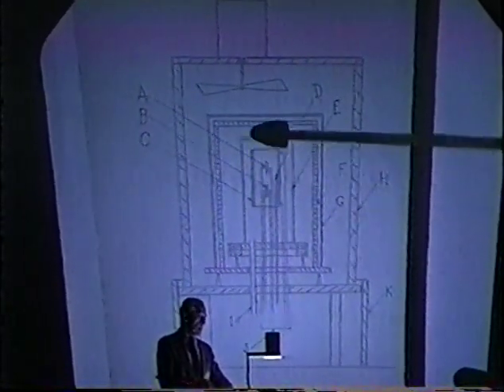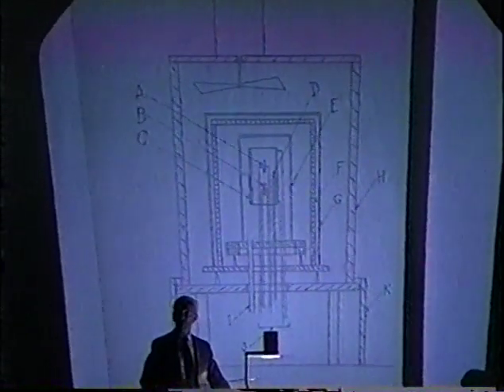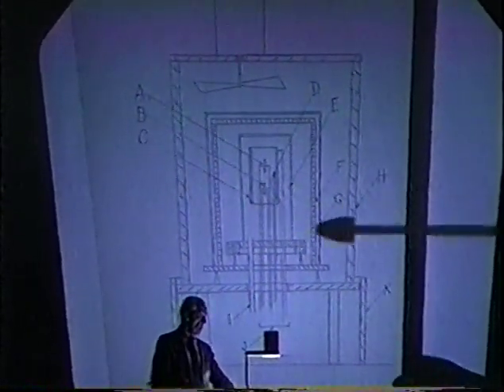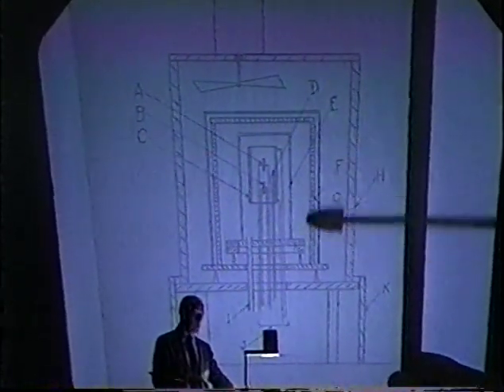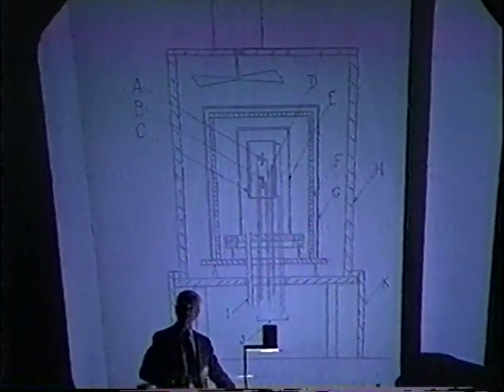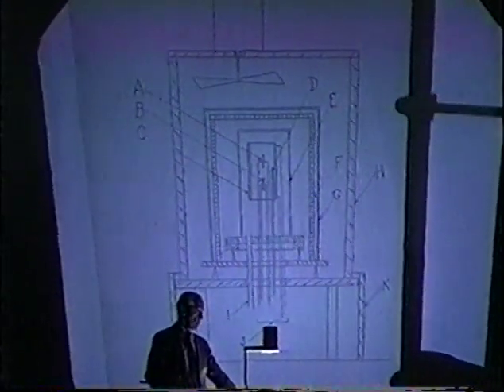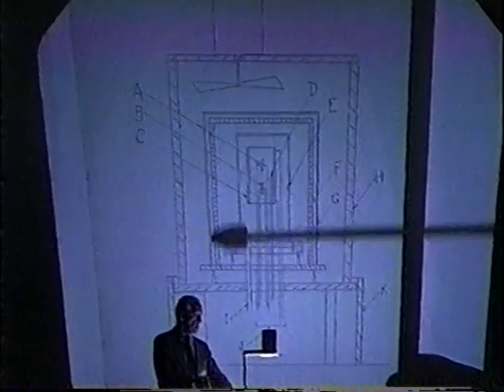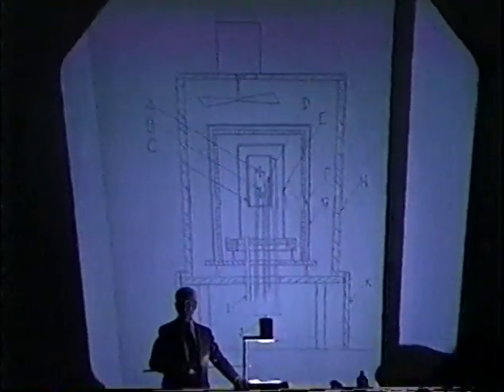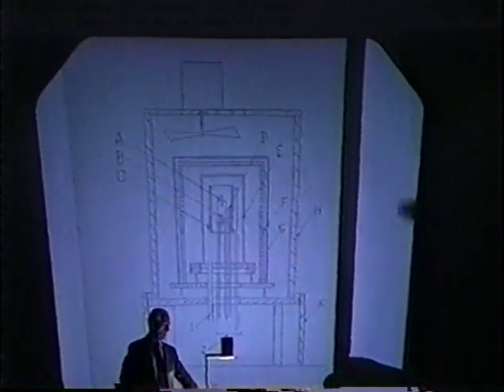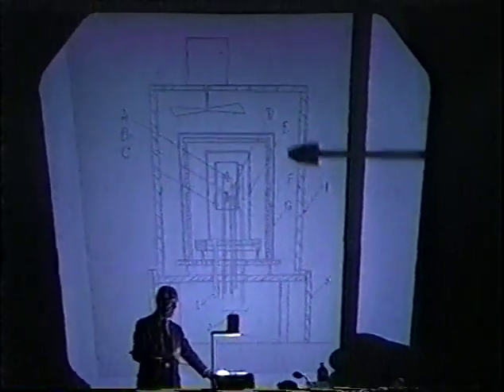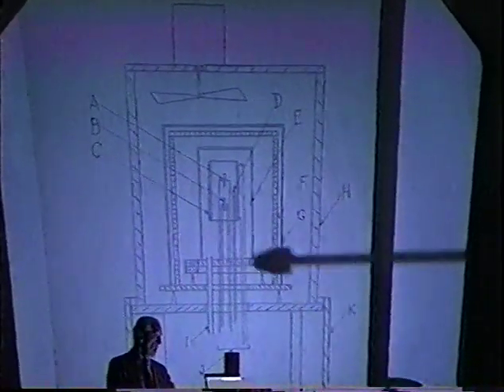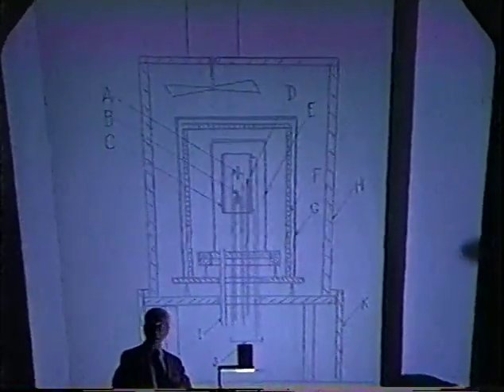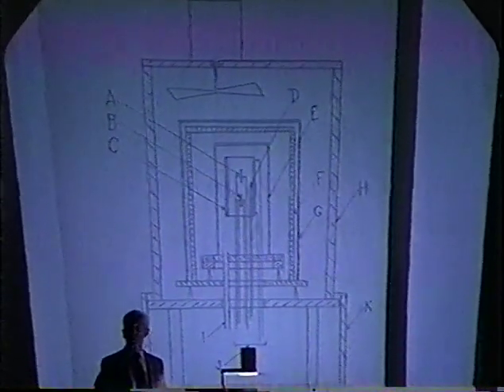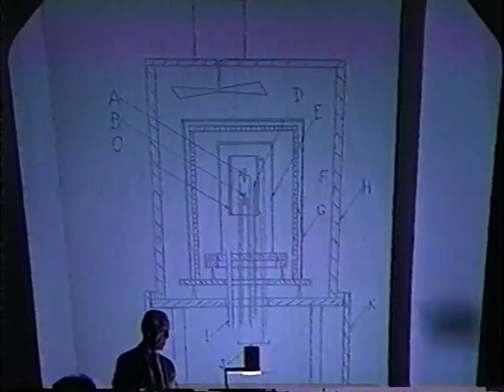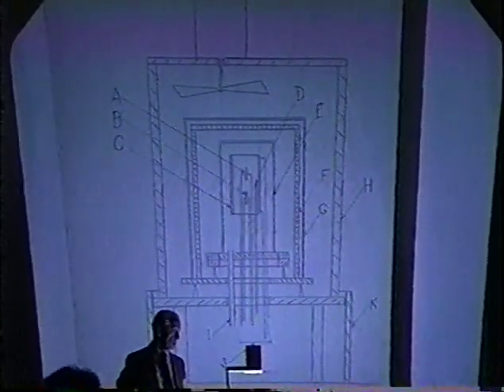This is contained inside of a stainless steel jacket, which can support high vacuum or high pressure gas. In turn, that's surrounded by what I call the Seebeck system, or the Seebeck box, and I will show that to you in more detail in the next transparency. Around the Seebeck system, which consists, by the way, of 710, I think, thermocouple junctions distributed over the 5 surfaces of the box, is a copper box whose function is to smooth out temperature variations as felt by the Seebeck system.